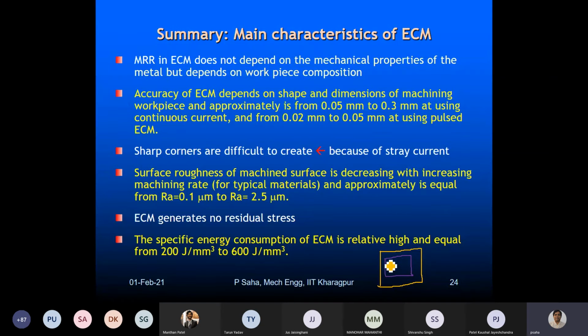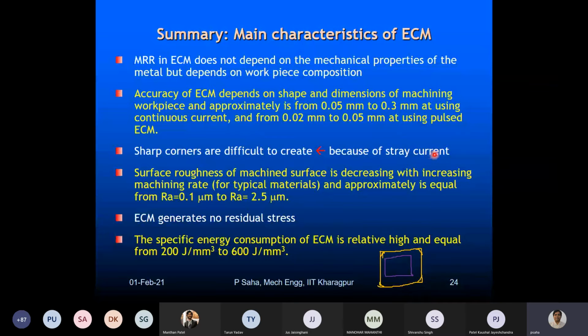Because at the corner your charge density is more, these portions will be machined much faster as compared to this gap. These corners will get machined much faster as compared to other areas, so that the sharpness will be lost. So although we quote this tolerance, whenever sharp features come, ECM will compromise the shape, because the features nearest to the sharp tool get more machining over here. So sharp corners are difficult to create. And there is also the stray current, because here both sides machining will be there and some stray current will be there.